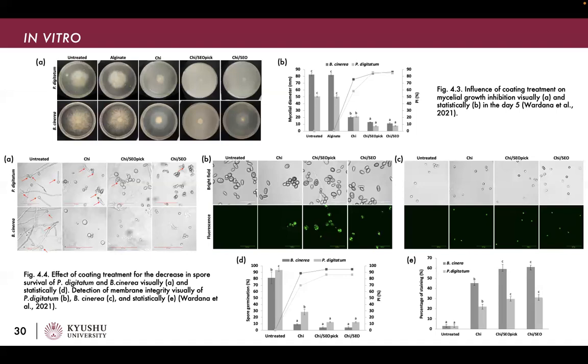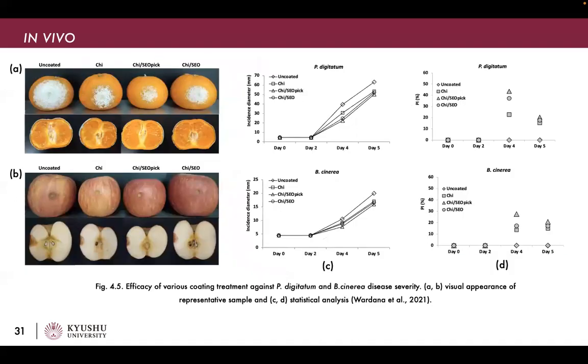And then chitosan may inhibit the loss of essential oil due to the environment exposure. It was confirmed by membrane integrity test with the aid of propidium iodide fluorescent dye. The coherent result was obtained from in vivo test using tangerine and apple. Again, there was clear evidence of appropriate level of chitosan as a stabilizer and the improvement of antifungal action.